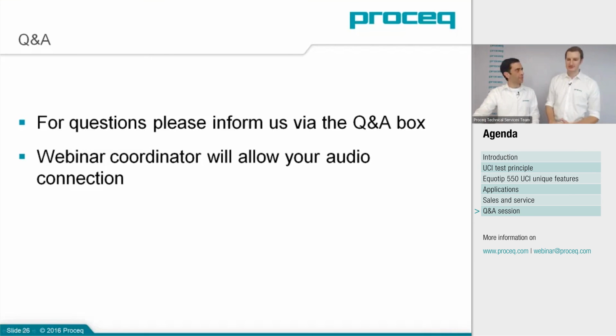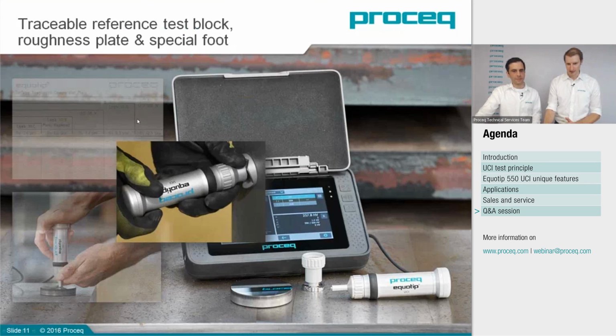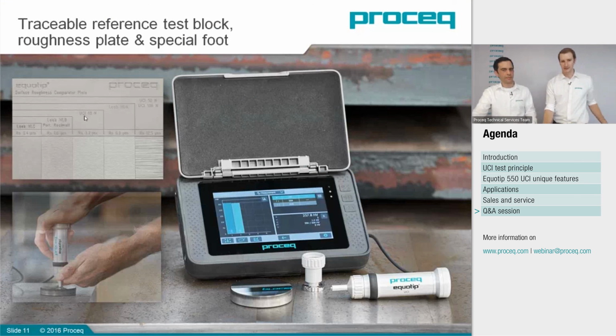The roughness, the acceptable roughness, depends on the hardness of the material and, of course, also on the test load that will be used for the measurement. So I would like to go back to the accessory slide and show you the roughness comparator plate. I don't know if you can read the values on this plate, but we have here in the middle field, this one is for UCI HV1, and the average roughness of 3.2 micrometers is acceptable. For UCI HV5 on the right side, 12.5 micrometers average roughness is acceptable.